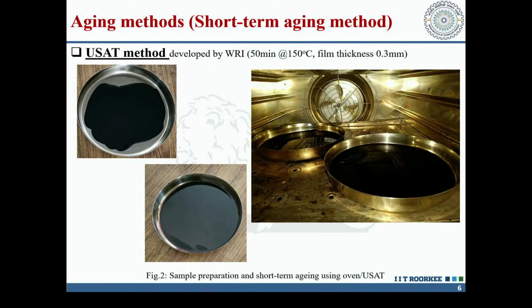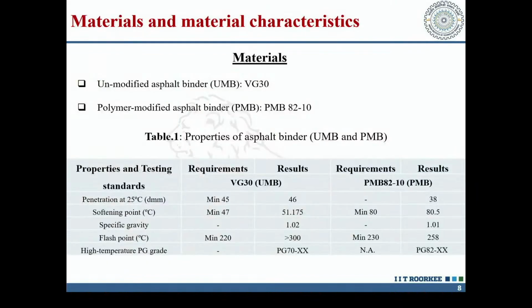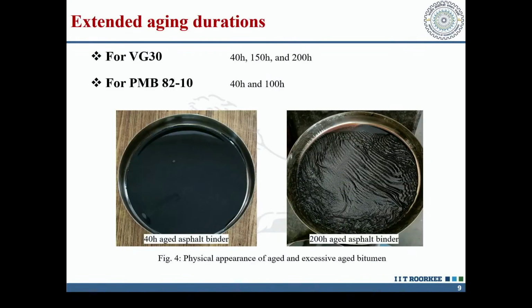And you can see here, these are the materials which we have used for the unmodified binder. We have taken VG30. For polymer modified asphalt binder, we have taken PMB 82-10. Basically, in the market, by the commercial name, PMB 82-10 is not available. The numbers we have given based on the testing on the DSR by finding out the high PG temperature. So high PG temperature in this case was found to be 82, and -10 is the lower temperature which has been taken. This number comes from the bending beam rheometer.